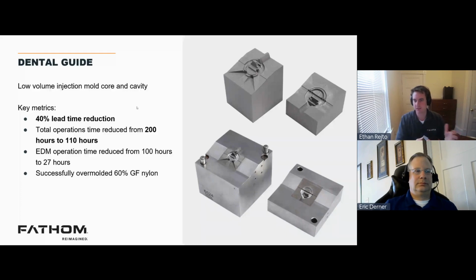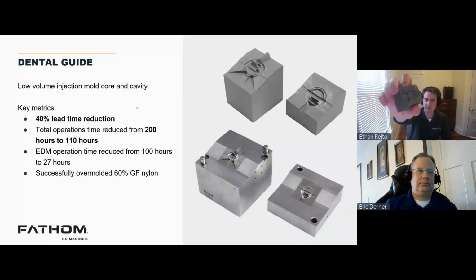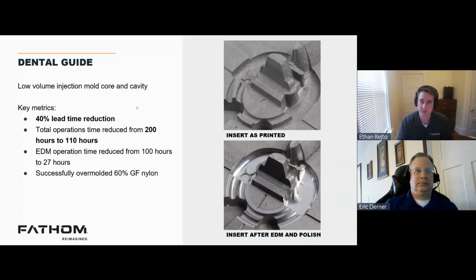So a huge savings that was provided by printing the part to almost complete here. And then this was successfully, it was actually an overmolding application, but again, a very, very abrasive material, a 60% glass-filled nylon. And this just speaks to the value of using Mantle, even when you need to do a little bit of post-processing. You can see on the right here, the insert as printed, and then after it was EDM'd and polished. You can see that just some of the features were too small to be printed, so they still had to come in and touch that up.